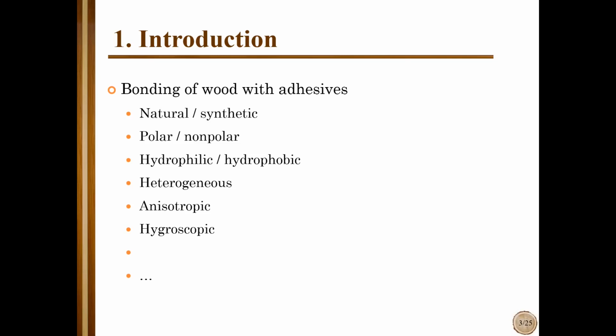Next thing which is important is that wood is originally more polar material, especially when we freshly prepare wood surface. But if it stays on the air, or if it oxidizes, or if it's, let's say, contaminated with some substances, it can become more non-polar. Another thing, hydrophilic and hydrophobic character of wood, especially wood which is heat treated or thermally modified, becomes more hydrophobic, which can present some difficulties in the bonding process.